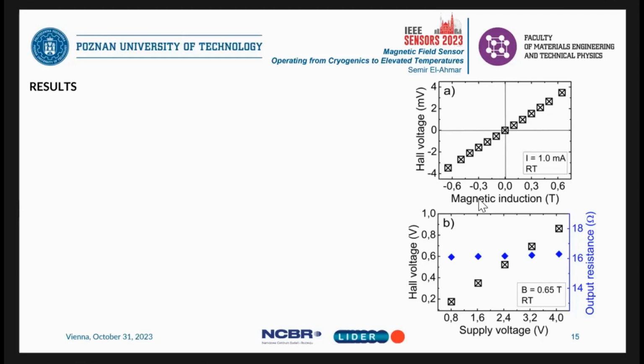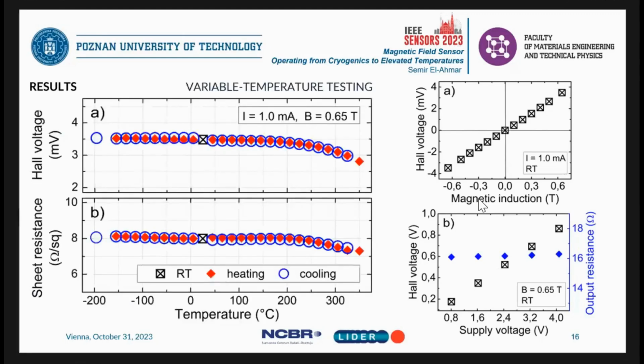And finally, this is the double graph of the basic electrical parameters of our sensor, Hall signal and sheet resistance, in a very wide temperature range from liquid nitrogen temperature up to 350 Celsius degrees. Each of these parameters shows two courses, heating and cooling from room temperature, marked with blue and red. And we can get a few pieces of information from this graph. First of all, we know that our sensor is operational in this whole temperature range, which is very good.